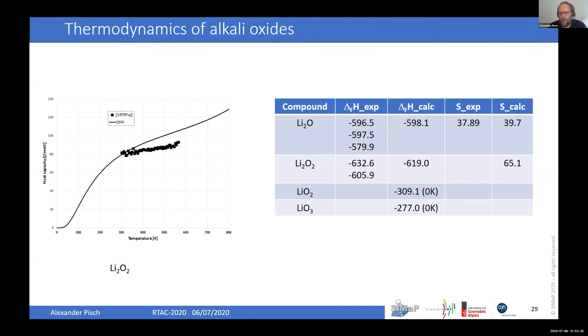Again, you can probably make the samples, and if you have the samples quenched in this high pressure state, you can measure the heat of formation and thermodynamic properties, but really directly measuring in the high pressure state, I think not. Crystalline properties, so the crystal structure and lattice parameters, this you can do. And this has been done. There's a lot of work in the literature, and you can compare that to calculations, but really measuring high pressure thermodynamic data is complicated.